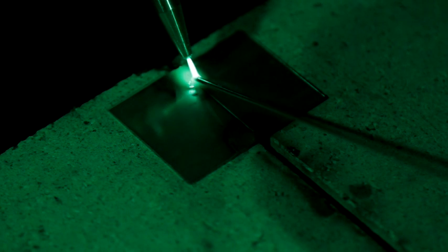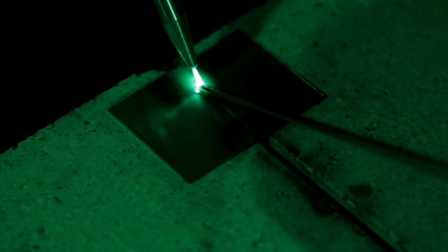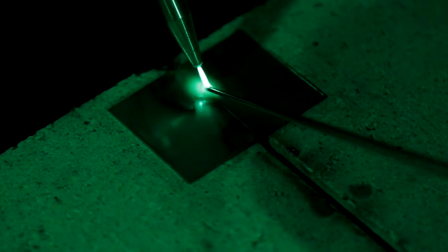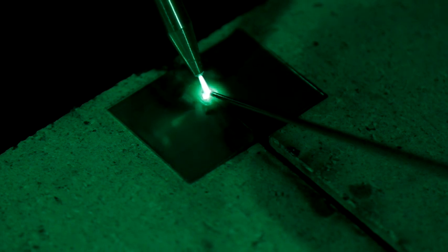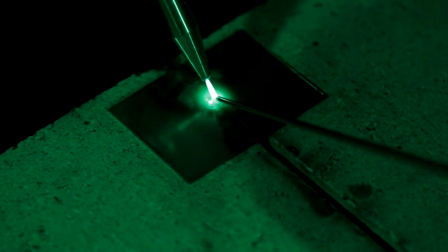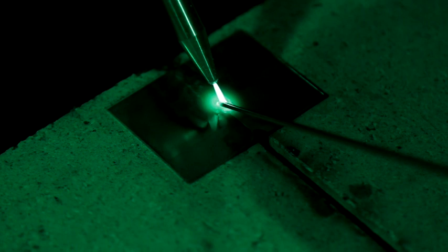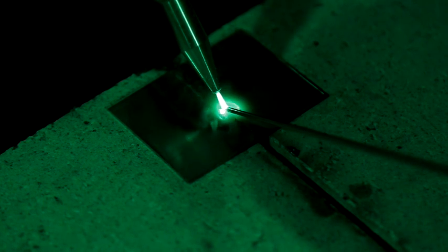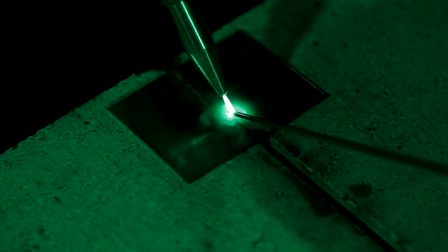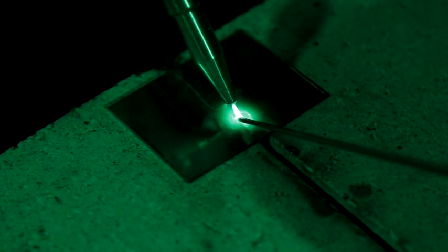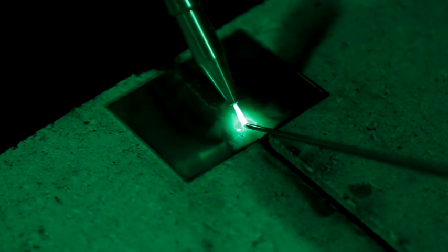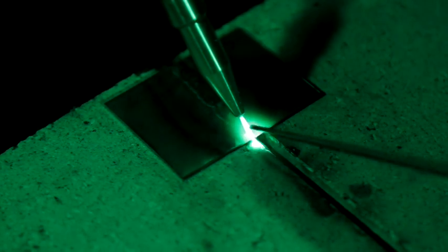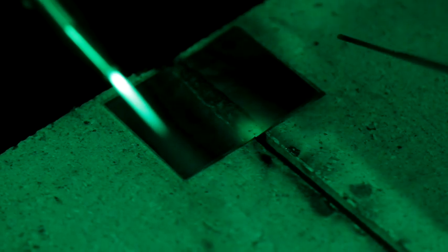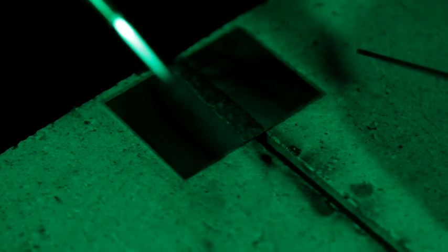Now, even on that stainless here, guys, we're welding with that little inner cone right there. So you just want to keep all the heat on the rod. It's sort of like brazing, except it's a whole lot easier. You're getting 100% penetration on it. And again, you can go from 4 thousandths thin all the way up to about 3/8 on that stainless.